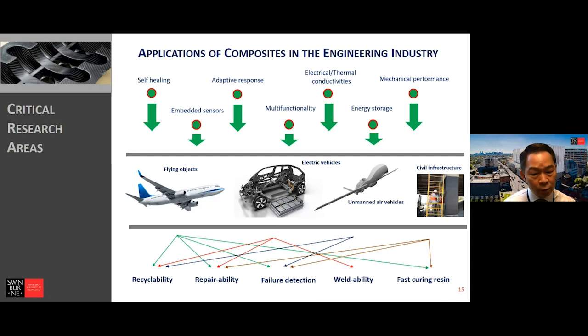How to determine or detect the failure? Whether we can weld the composite, like metal. Fast curing resin, as I mentioned already. So these five areas are the important areas for the industry, not only for research, but for the industry. And when we can solve all these problems, there will basically be no problem at all in using composite material in industry. Because we have to compare the traditional metal structure and the new composite material, so you have to compare the pros and cons. Why do people still want to use metal and not use composite? Because all these five areas are very important.